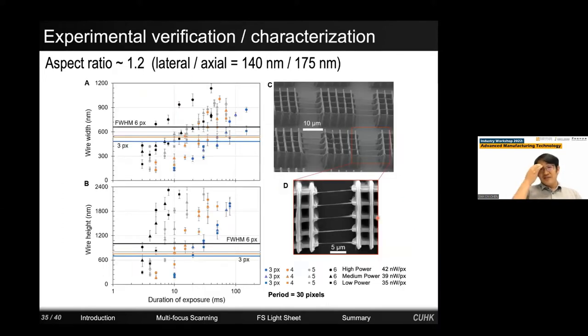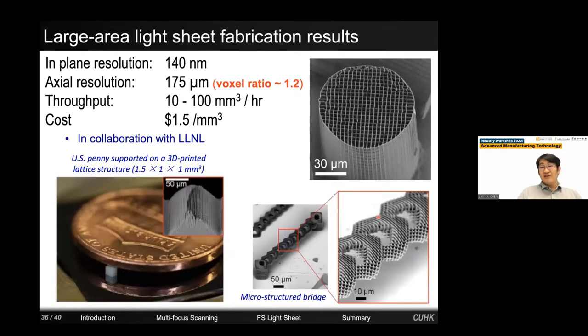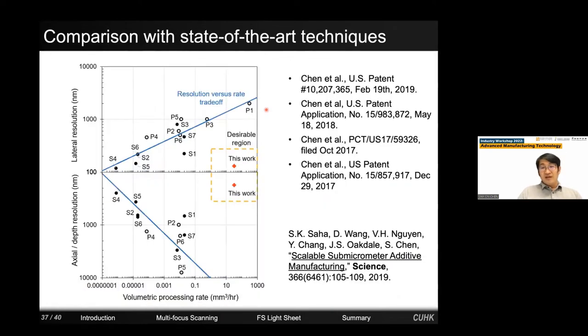printed structures. By carefully studying the laser dosage relationship with structural integrity, we can create all kinds of three-dimensional structures. For example, this column has a diameter roughly equivalent to your hair, and there are various large-scale structures that could not be created in the past. Also the cost is reduced by around 95%, and the throughput is now roughly 100 cubic millimeters per hour, versus originally 0.1 cubic millimeters per hour. Okay. As a result, this work was published in Science magazine.